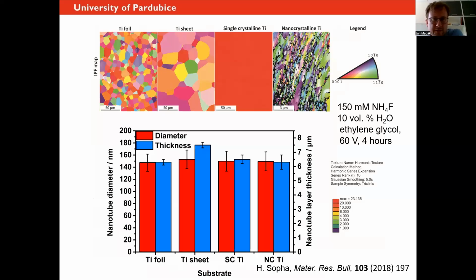Just last information about the substrate. Also, you might have single crystalline titanium or nanocrystalline titanium, and the good news is that the tubes also grow on these substrates. So basically, this polycrystalline titanium foil is the most typical substrate that you take. I would say 99% of cases is this substrate, but sometimes you want to take thicker sheet or single crystalline sheet. No matter what you do, if you use the standard conditions, the diameter and the thickness will be more or less the same.